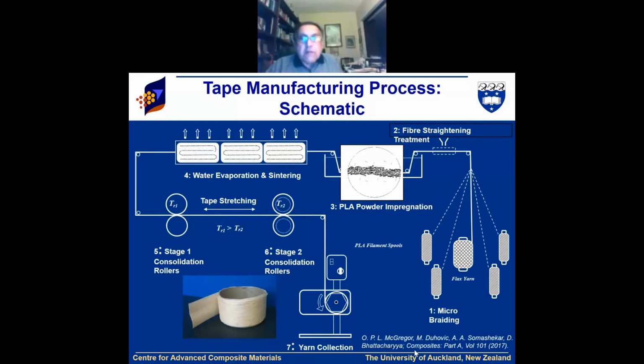This is a PhD of Oliver McGregor, that we took various spindles of flax fibers with powder impregnation, just like our kite flying. The idea really came from there. Manja, this powder, this is the powder impregnation. Powder is there, and it goes through. Instead of any solvent, we use water, and then water gets evaporated, but actually these powder, PLA powder, get clung to this fiber as well. And then because multiple spindles are there, micro braiding, it can become a tape, a wide tape like that.